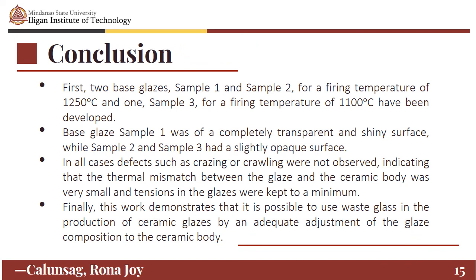For the conclusion, first, two base glazes, sample 1 and sample 2, for a firing temperature of 1250 degrees Celsius, and one, sample 3, for a firing temperature of 1100 degrees Celsius have been developed. The base glaze sample 1 had a completely transparent and shiny surface, while sample 2 and sample 3 had a slightly opaque surface. In all cases, defects such as crazing and crawling were not observed, indicating that the thermal mismatch between the glaze and the fired ceramic body was very small and tensions in the glazes were kept to a minimum.